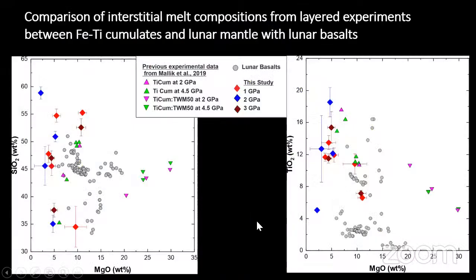When we compare the composition of our interstitial melts with those of the lunar basalts, these are the results from our study: at 1 GPa, the red diamond, 2 GPa, the blue diamond, and 3 GPa, the maroon diamond. And these are the results from the study by Mallik et al., who conducted similar experiments with a mixed composition. Our results are plotted in Harker diagrams, oxide versus MgO. We can see that the SiO2 content of our melts is at par with the lunar basalts, almost covering the entire range of variation. These gray circles are the lunar basalts.